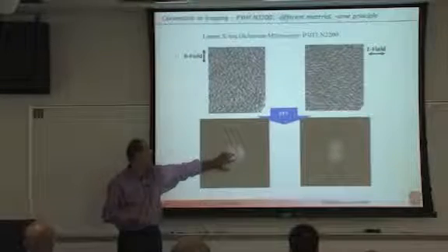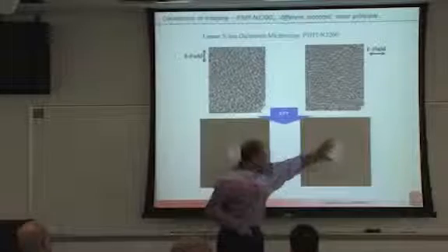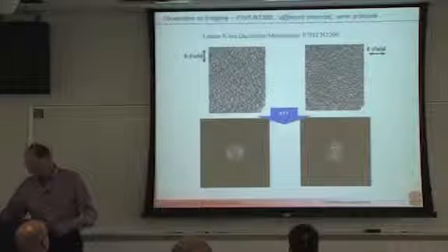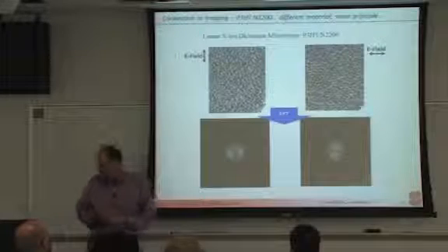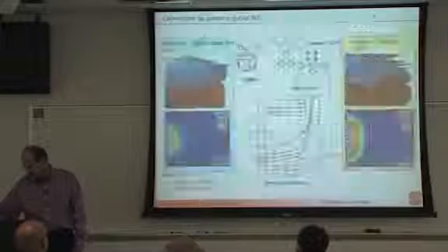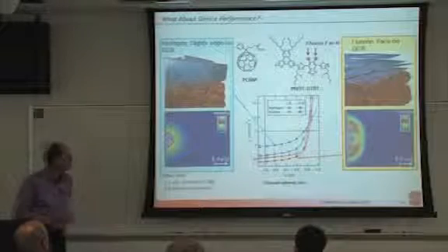If I look at the Fourier transform, which is what I would expect to get in scattering, I get lobes that are horizontal here, and I get the lobes that are vertical here. So I think we are on a way to create a coherent picture of how to interpret that. The first time we've observed this scattering anisotropy was maybe a year and a half ago. So that hasn't really been seen, but I think it will be a great tool to look at devices.